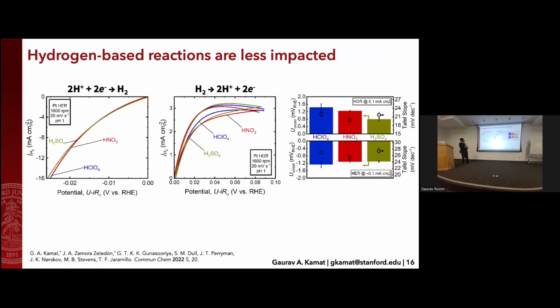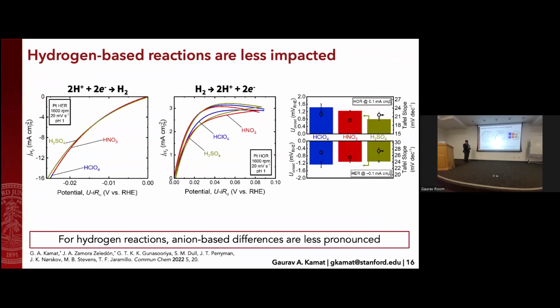But the interesting thing is if we do the same experiment at a lower potential where you have hydrogen now present, now we're looking at the hydrogen evolution reaction, the one I showed at the very beginning, and also its opposite reaction, which is hydrogen oxidation. We don't really see that much of a difference in magnitude compared to what we saw before. So for hydrogen reactions, you have anion-based differences that are a little bit less pronounced.